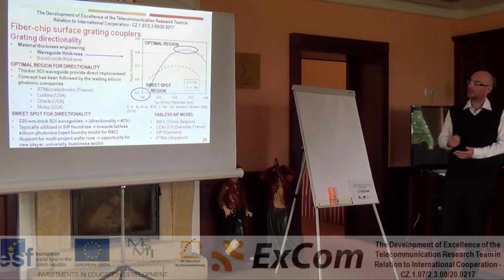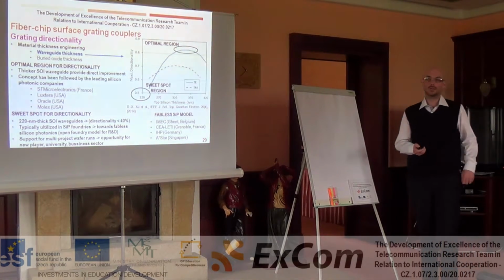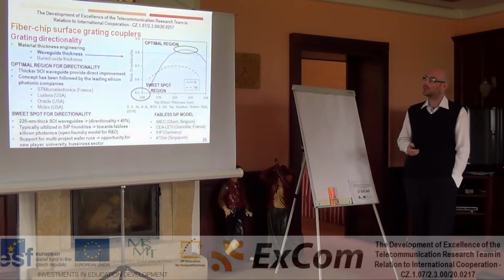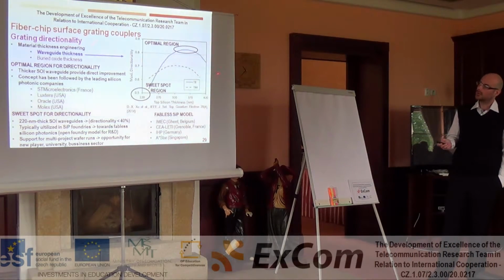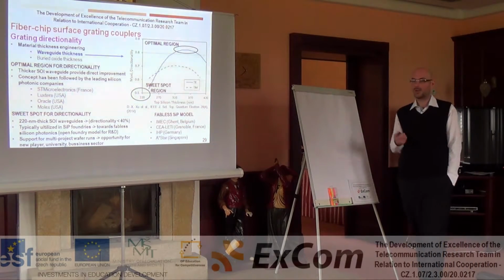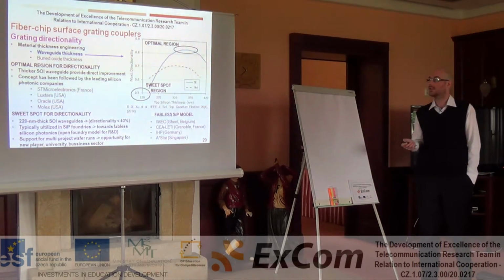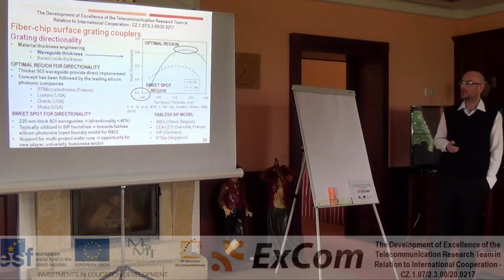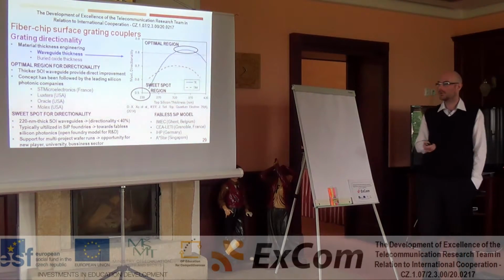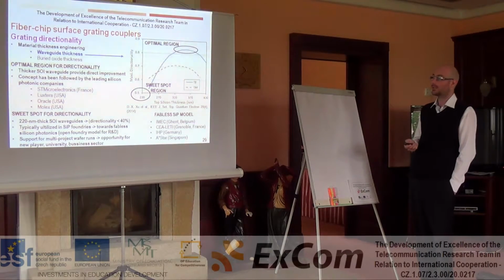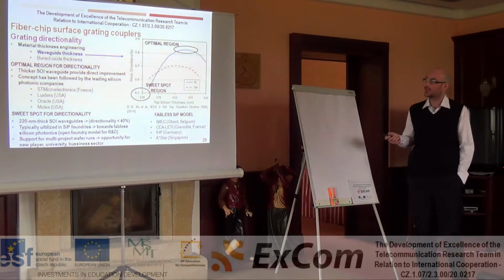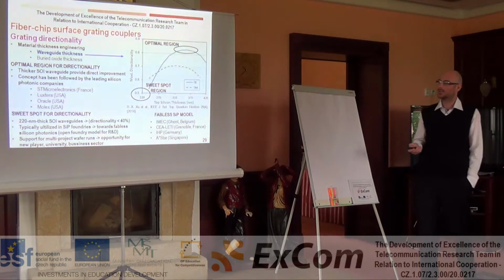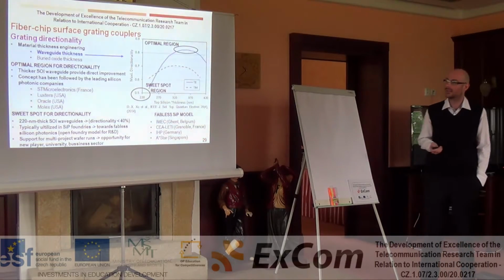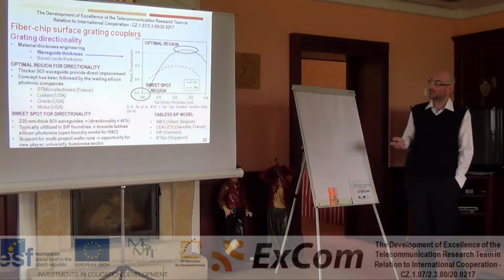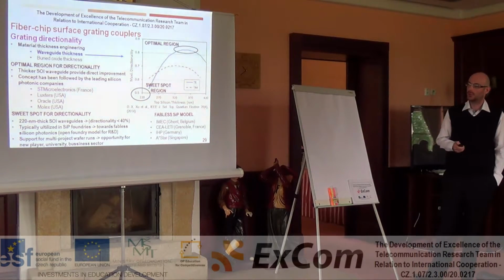Grating directionality or grating diffraction efficiency very seriously depends on the waveguide thickness. As you can see on this figure, the optimal region for grating couplers that have a very high diffraction efficiency is around 350 nanometers. Thicker silicon waveguides can provide direct improvement in terms of grating directionality. The concept of using thicker SOI waveguides has been implemented, for instance, by companies like STMicroelectronics from France, Luxtera, Oracle, or Molex from the USA.